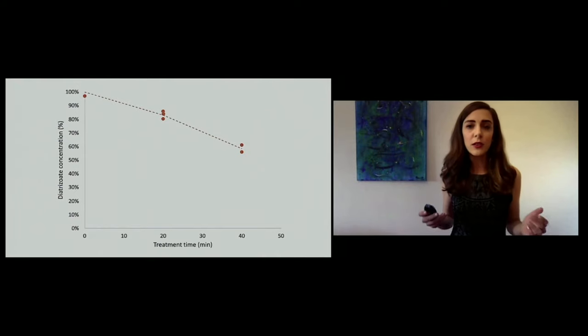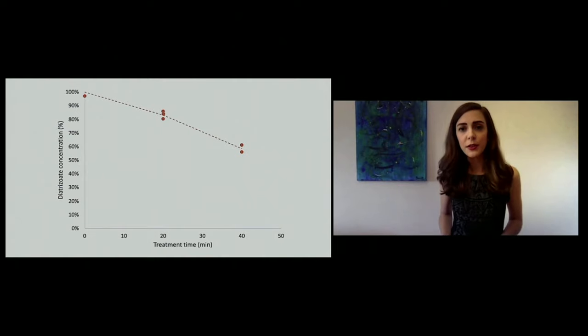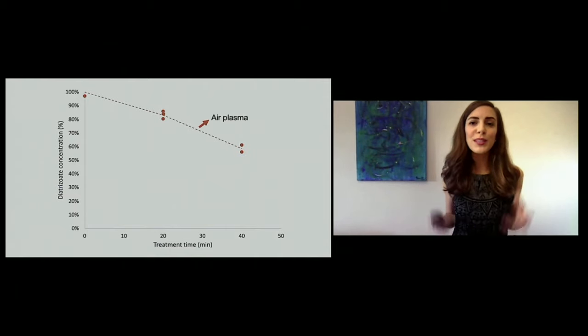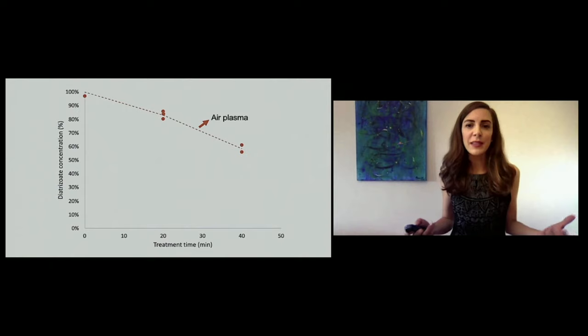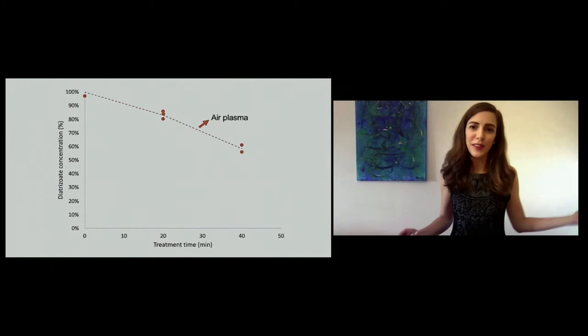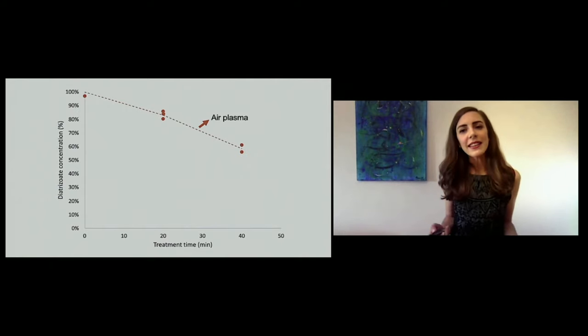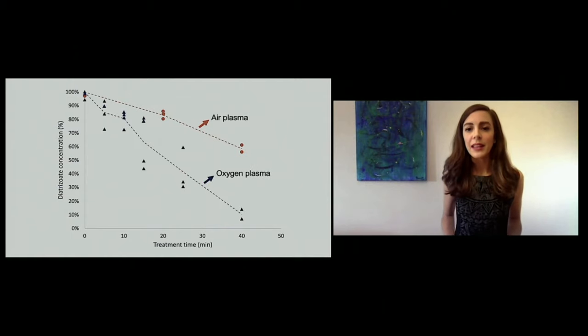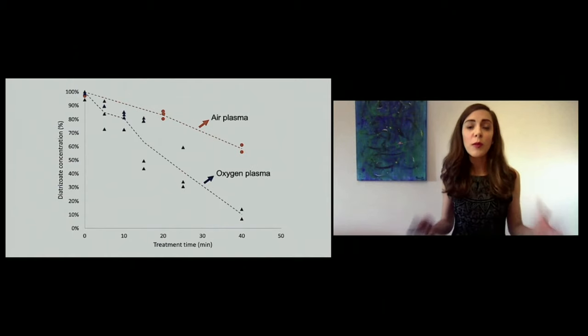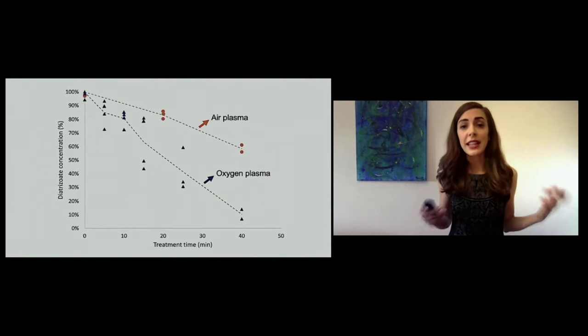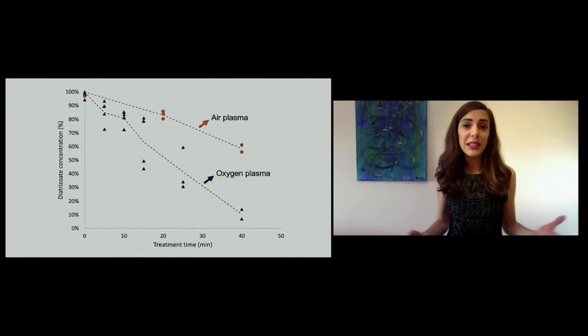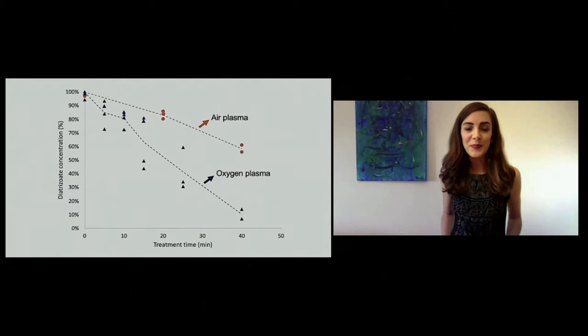And as we cannot improve the voltage and pulse frequency further, what we could do is change the type of gas, which I mentioned earlier is quite important. Here, I was using an air plasma, the same type of plasma that I was using for the previous experiments that I showed you today. Well, by replacing this air plasma with an oxygen plasma, I was able to remove the dye almost completely after 40 minutes, whereas with air, we removed less than half. So this is really great news. Now we can remove diatrizoate in a reasonable amount of time.